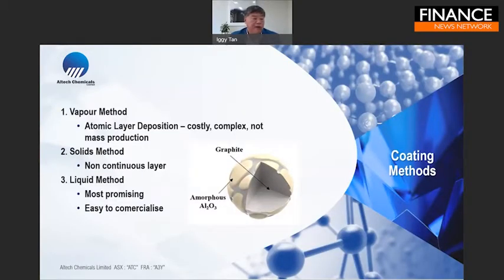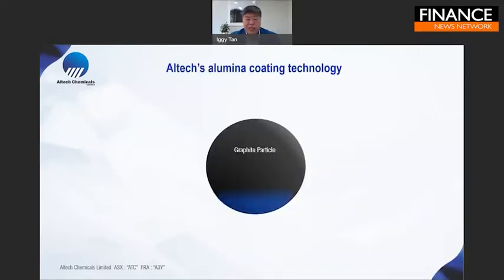Now, there are 3 ways of coating alumina onto graphite: the vapor method, the solid method, and the liquid method. The vapor method is called atomic layer deposition. It's costly, complex, and is not suited for mass production. We're focused on the liquid method using our technology, and essentially we can coat a graphite particle with a very thin layer of alumina, in fact around 2 to 3 nanometers.